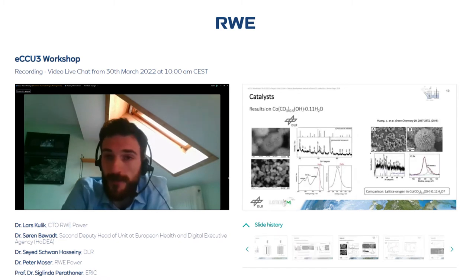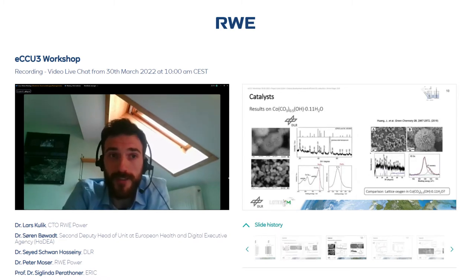Starting with the left one, on slide 10, we can see the results that we have carried out. On the left side, the results of DLR, on the right side, in comparison to the literature. We basically reproduced the synthesis procedure and also got these urchin-like nanoparticles. By looking at XRD peaks, the characteristic peaks were also there. And for the XPS, we got similar results. The only difference, maybe going into more detail, is that we had some lattice oxygen present in the paper, which we could not really recover. But looking at the structure, it's also questionable if there is any lattice oxygen within. Probably this would lead too far here.